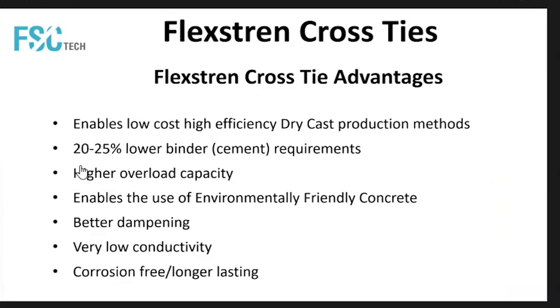Because the dry cast production method is an immediate stripping process, you normally have a water cement ratio varying between 0.25 and 0.32, 0.33. Because of the very low water cement ratio, for the same strength level you can normally get between 20 and 25% less cement. You have a lot higher overload capacity.